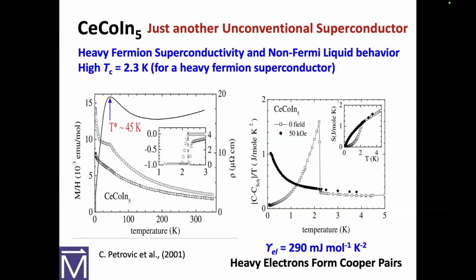I think you're very familiar with the heavy fermion nature of the transport and the heat capacity, and it's about 85 times the free electron mass in cerium cobalt indium 5, and the heavy electrons form the Cooper pairs. I want to point out that at about 45 K, T star is where you start getting the real strong hybridization, and you all know this, between the conduction electrons and the f levels. And then you get this strong drop in the resistivity, and Tc is down here at 2.3 K.